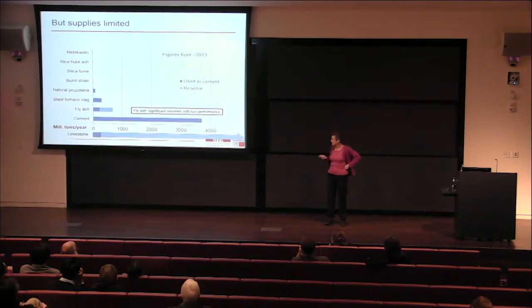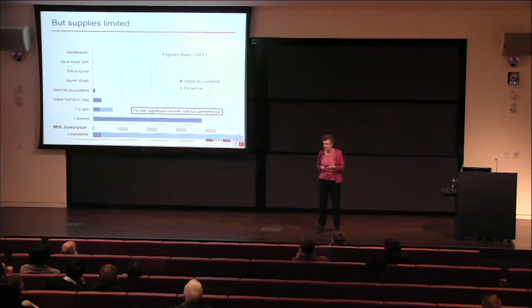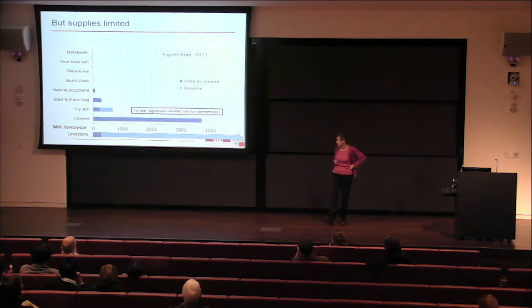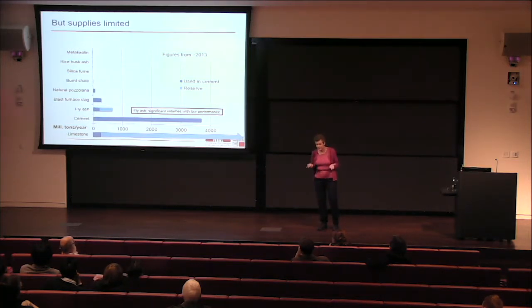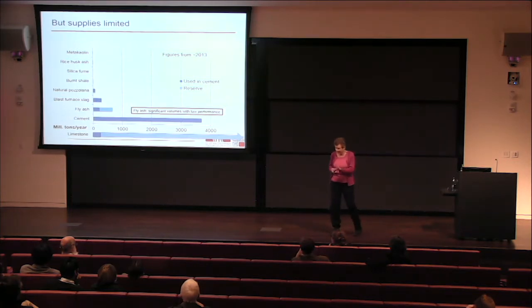And this situation is probably going to get worse because, as you saw at the beginning, making steel produces a lot of CO2. There's big pressure on steel makers to reduce CO2, and one way they do that is by recycling. And so there's going to be less and less slag available in proportion to the amount of cement. And fly ash, okay, there's more fly ash available, but the quality is very variable. So today we can only use about 1/3 of the fly ash produced in concrete. And perhaps we can go further with that, but generally, there's a lot of it which has really very low performance, doesn't really react any more than putting in sand or something like that.